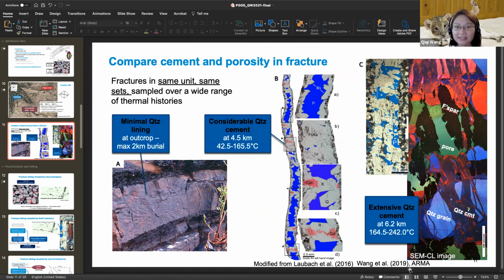So in those cases, they value a lot of the fracture porosity when they calculate approximately how much production they can generate from those very deep and really tight reservoirs. But in my case, I would say in this Nugget sandstone, because it can be produced conventionally, the fractures here just add to the permeability and porosity. And Steve, you're right, fracture porosity in the Nugget case might not be as important.